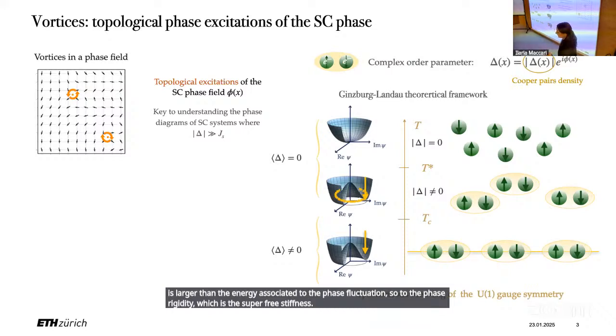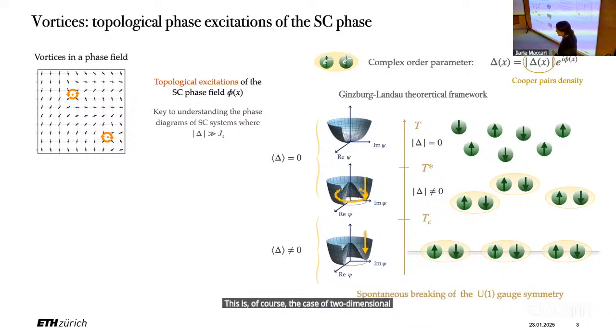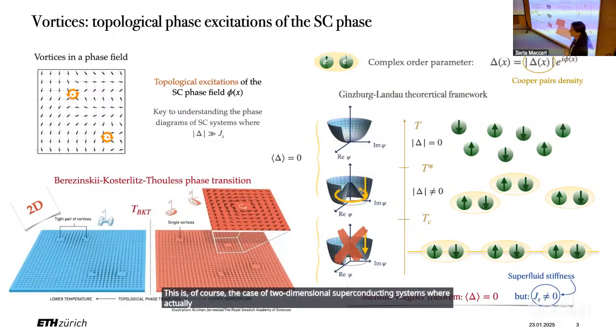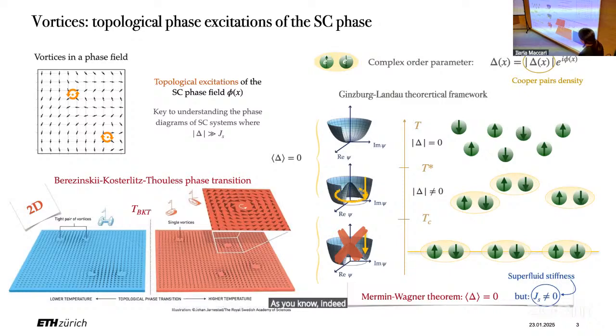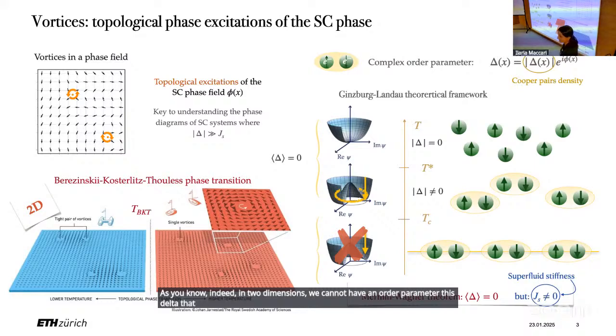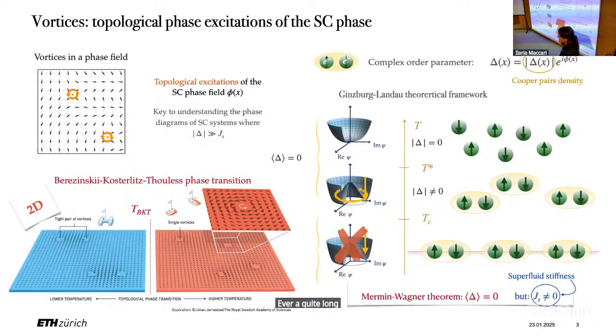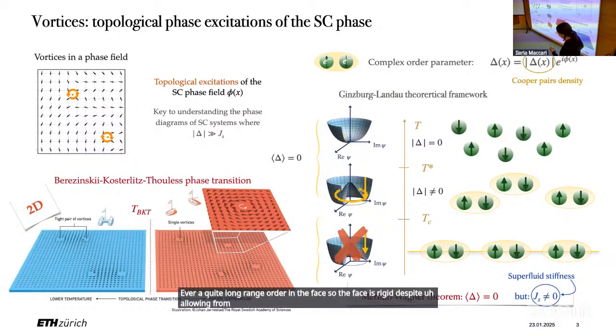This is, of course, the case of two-dimensional superconducting systems, where actually the whole superconducting transition can be described in terms of the unbinding of these topological objects that are vortices and antivortices. As you know, indeed, in two dimensions, we cannot have an order parameter, this Delta, that becomes finite from zero at any finite temperature because of Mermin and Wagner. But we still have a superconducting state due to the fact that these Cooper pairs have a quasi-long-range order in the phase, so the phase is rigid, despite allowing smooth deformations of the phase.